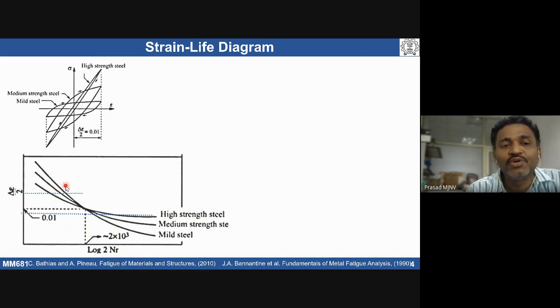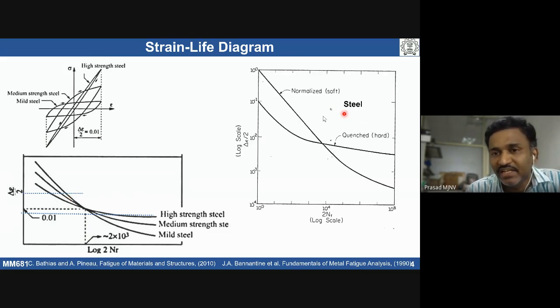So if we have a good amount of ductility, we can see the number of cycles required for the complete failure of the component is going to be more. Similarly, another example: if I take a steel, one has been normalized by heat treating the material to austenite temperature and cooling in air. In the other, you heated the material to austenite temperature and quenched it rapidly. That basically gives a martensitic structure.